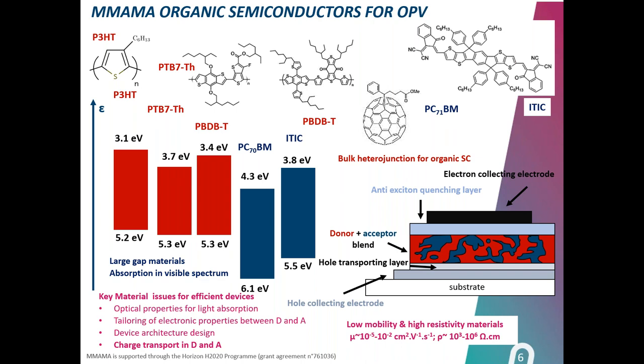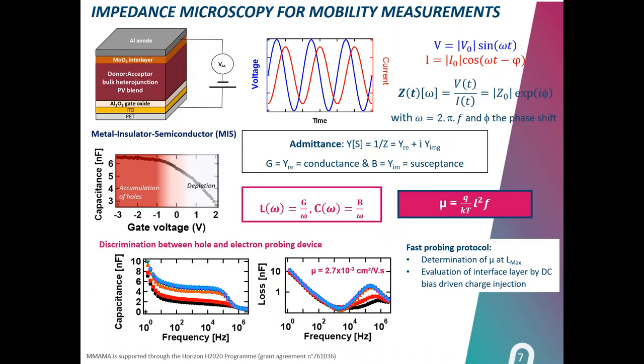And the idea was to see whether we could use microwave characterization methods to evaluate the electrical properties of these materials and determine the carrier mobility, which is a figure of merit. So you have typically the scale of carrier mobility and resistivity associated with materials at the bottom of the slide. The first method that has been developed was impedance spectroscopy.